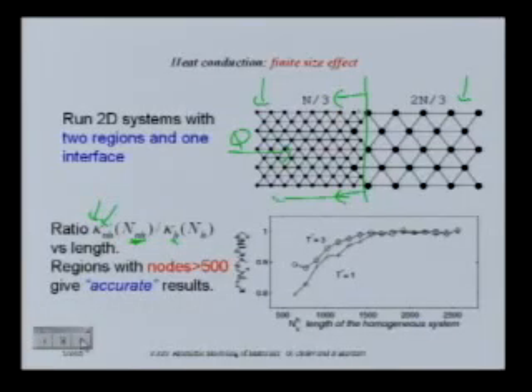But it's interesting, if you show this as a function of the length of the homogeneous system, you do better and better as this system gets bigger. That makes sense, because then the interface becomes less and less important. But look at the size here: to get up to about 1, you need about 1,500 atoms in the homogeneous region. So this is a major problem with phonons in general. I think of any atomistic-level phenomena, phonons probably have the largest length scale. The phonon mean free path at low temperature is enormous—it's thousands of atoms far.